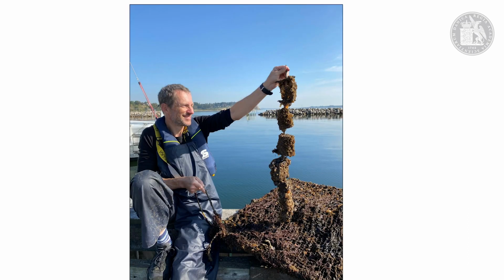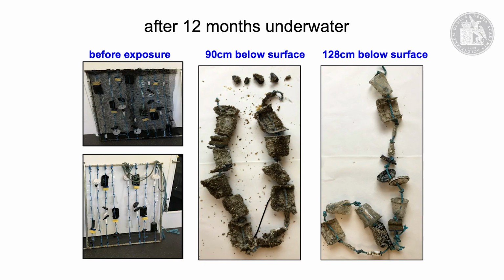Clearly there's a lot of growth on these samples, even though they've been protected by a net and a mesh. But after, I think, 12 months, they look completely different to how they did when they were put down. They actually look, I think, very beautiful. They've all kinds of barnacles, and we had to separate some mussels from them. They're completely coated. What's interesting is the deeper down they were, the more protected, the less growth they have on them. So these were 128 centimetres, just over a metre under the water, and this was just less than a metre. But the difference is amazing.